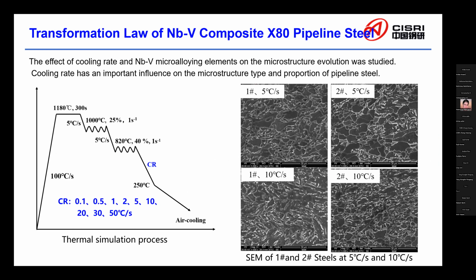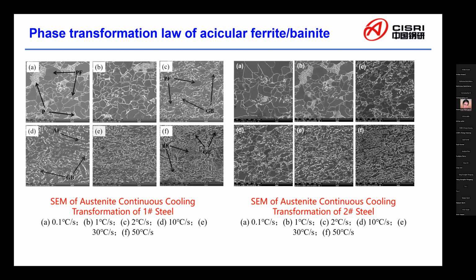The effect of cooling rate and the microalloying elements on the microstructure evolution were studied. It can be seen that cooling rate has an important influence on the microstructure type. Take number 1 steel, for example. When the cooling rate is 0.1 degrees centigrade per second, main microstructure are polygonal ferrite and pearlite. When the cooling rate is 2 degrees centigrade per second, main microstructure are polygonal ferrite and granular bainite.